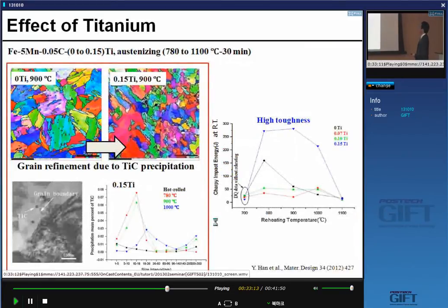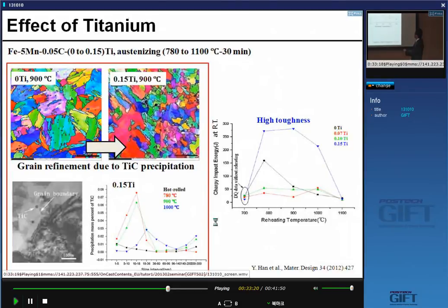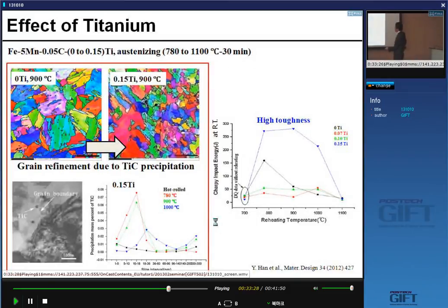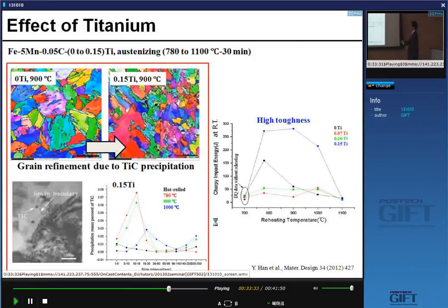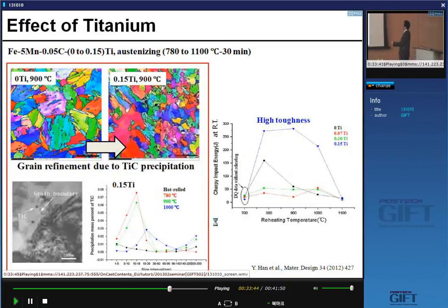Titanium effect: we added some amount of carbon and expected titanium carbide precipitation during annealing — and yes, that happens. There are small particles of titanium carbides, and these particles refine the grain size compared to steel without titanium, as confirmed by EBSD. When the annealing temperature is in an appropriate range, we have fine grains due to the titanium carbide precipitation, and the toughness of the steel was greatly improved.